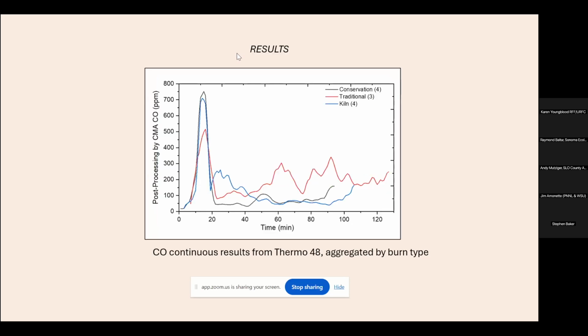CO, again, during the high consumption phase of the fuel, you get a very large peak in CO, and then it burns down, and CO is usually a function of smoldering emissions. For these fires, for the traditional, we see a bunch of peaks of CO, which may be related to the stirring of the fires. I'm not sure. And as you can see, the kiln fires were a lot lower in CO than the traditional.